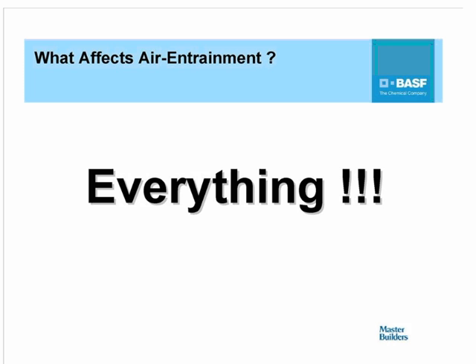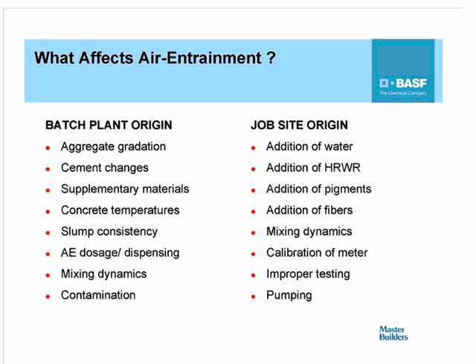With respect to things that affect entrainment, anyone who's ever worked with entrained concrete will know that they're extremely touchy, and pretty much everything that you can think of can affect the entrainment in concrete. These include things from the batch plant, such as the aggregate gradation, the cement changes, the use of supplementary cementitious materials, especially class F fly ash, depending on the carbon content and so on. And at the job site, things such as the addition of water, high-range water-reducing admixture, pigments, fibers, and so on, also affect entrainment. Pumping is also one thing that can affect entrainment, especially if we have a vertical drop at the end of the pump line.